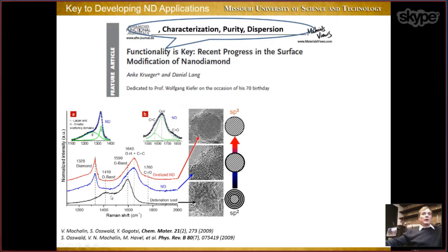And here I show for example, 3 different batches of material bought from the same manufacturer, but you see how different they are when we characterize them by Raman spectroscopy and by transmission electron microscopy. For example, in detonation soot, you will not see a peak corresponding to diamond in Raman spectrum at all. So you can easily come to a wrong conclusion that there is no diamond in this material because you don't see diamond peak, and Raman spectroscopy is commonly used to detect different allotropes of carbon.